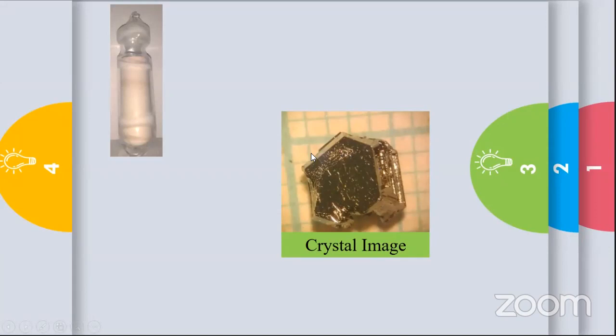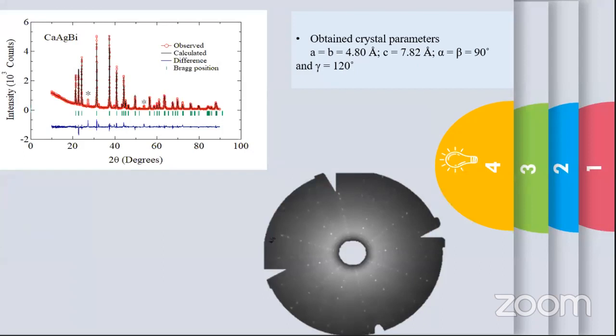And this is the real image. For basic characterization, we did powder XRD. The powder XRD shows that in the phase we only have a very small, tiny bismuth peak, because here we used bismuth as a flux. The Laue diffraction shows clear hexagonal symmetry in the crystal structure, which confirms that the grown sample is a single crystal.